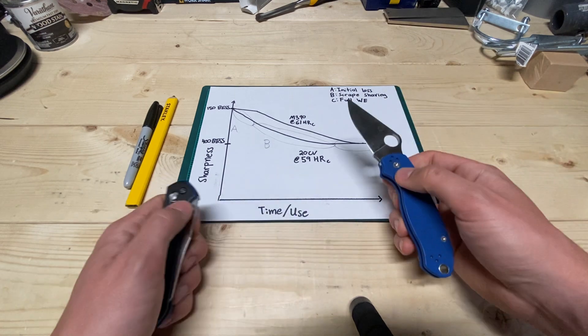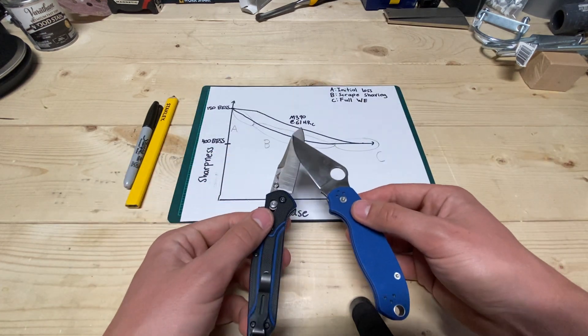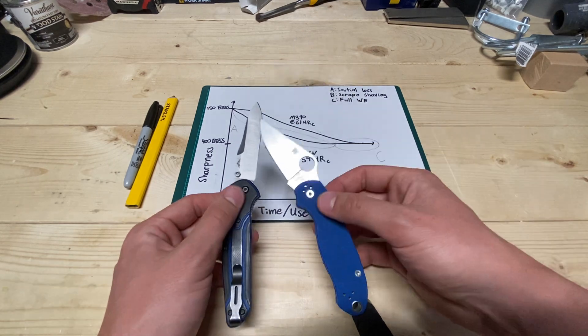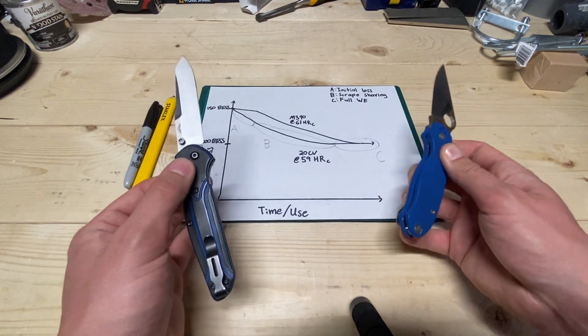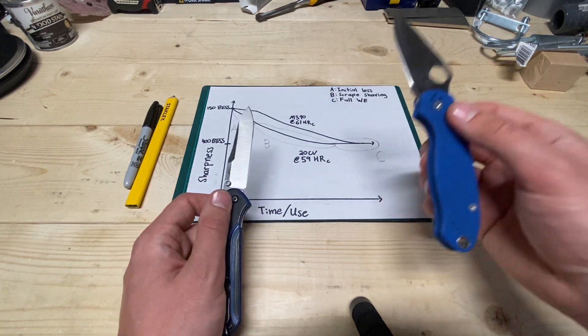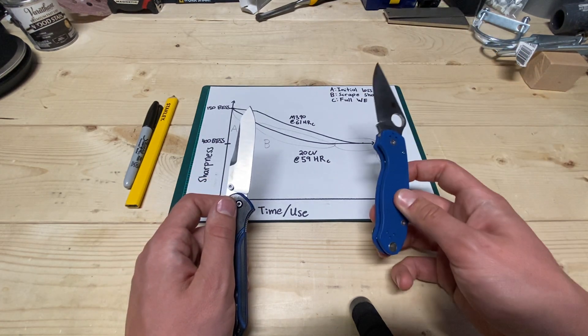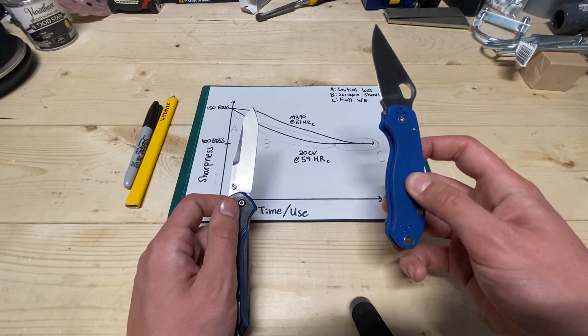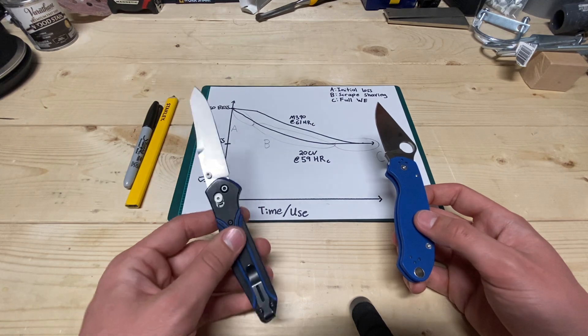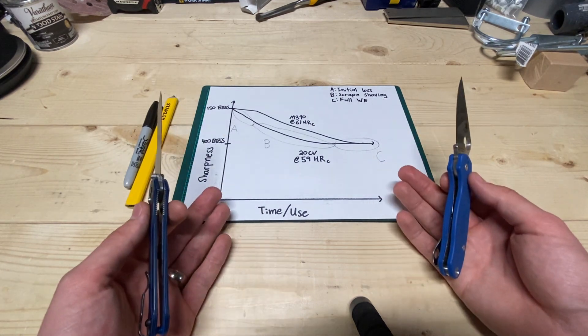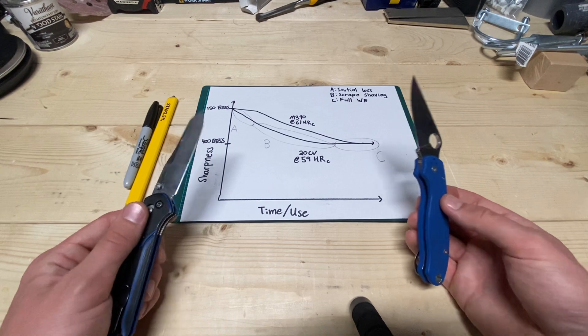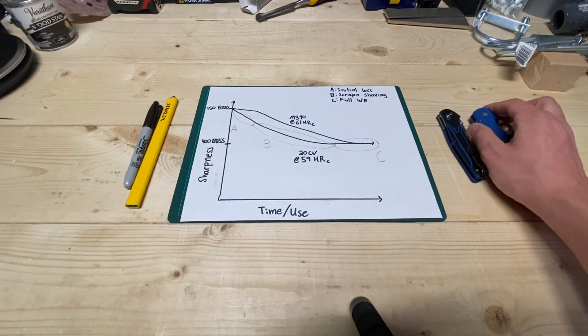So, to summarize the findings, the same steel, because these are analogs of each other, basically the same chemistry, if you heat treat it harder, roughly, there's a lot of nuance to that, but roughly, if you heat treat it harder, it will hold the fine edge longer, and after a certain amount of time, will reach the same working edge that the softer stuff will reach. That's pretty much it.